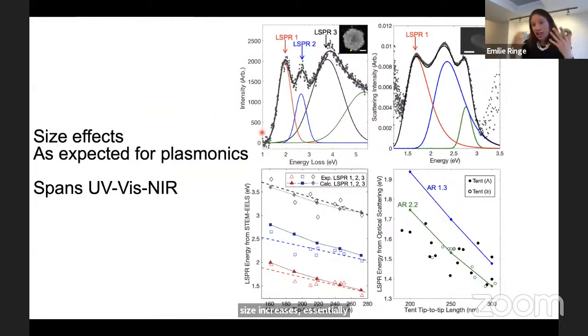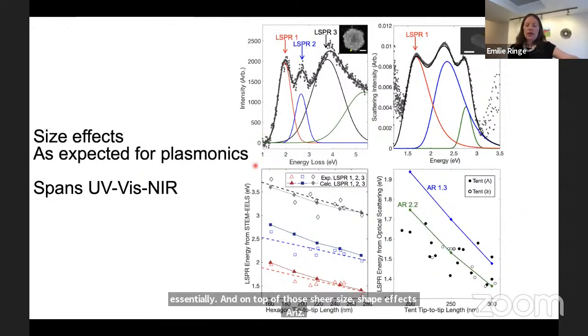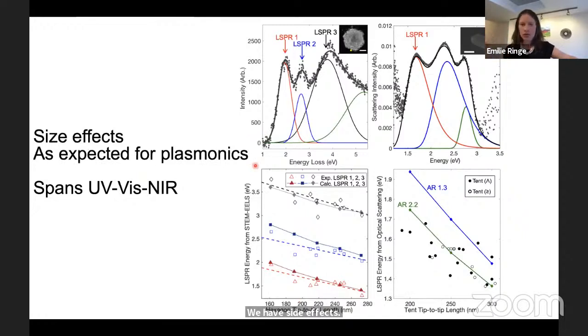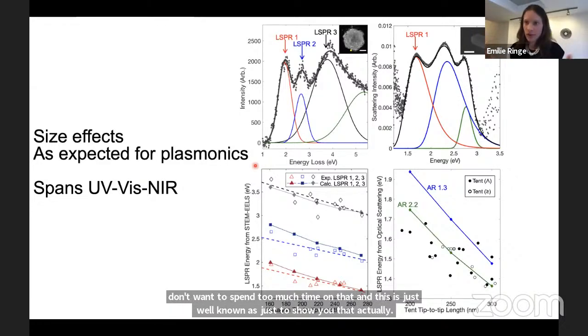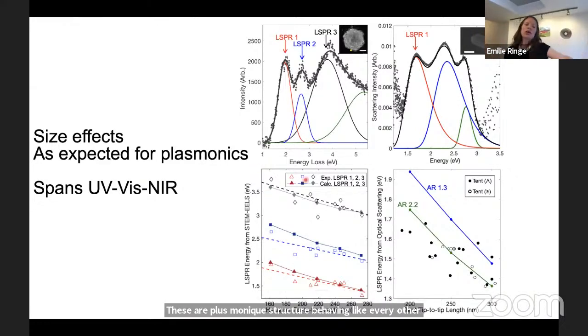On top of those shape effects, we have size effects. I don't want to spend too much time on that - this is just well known. It's just to show you that these are plasmonic structures behaving like every other plasmonic structure. So if you take this graph, what I'm showing is the plasmon resonance for our first mode, second mode, third mode in hexagons, showing that as the size increases, the plasmon resonance decreases.